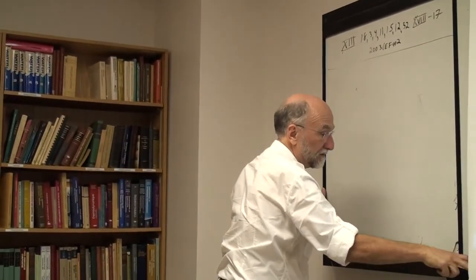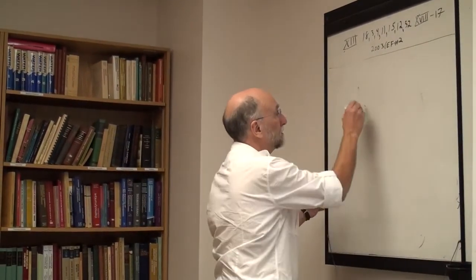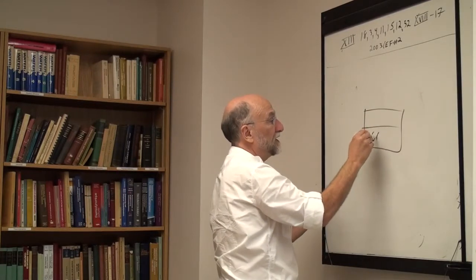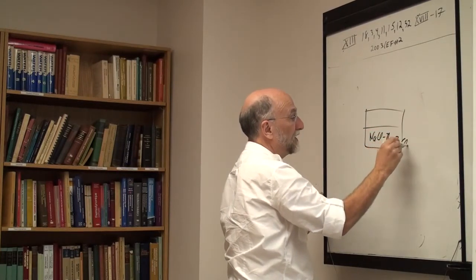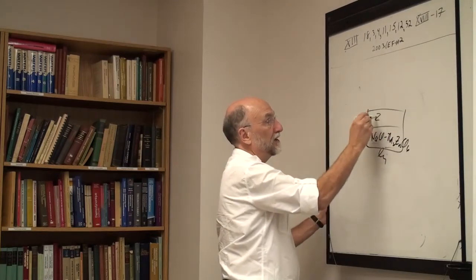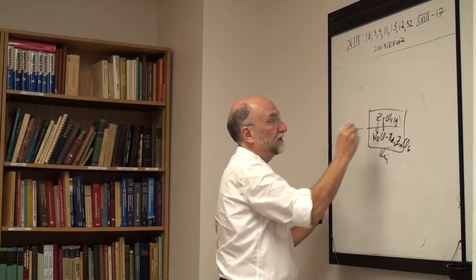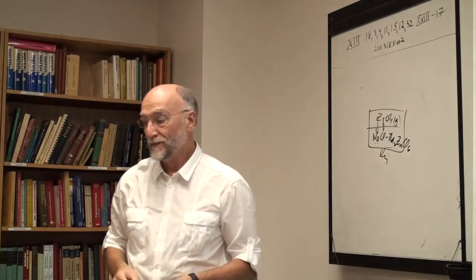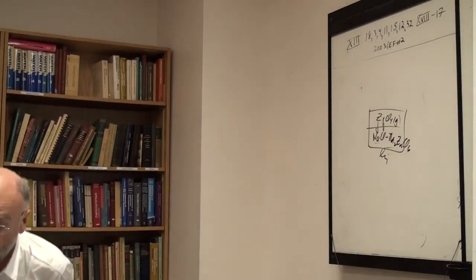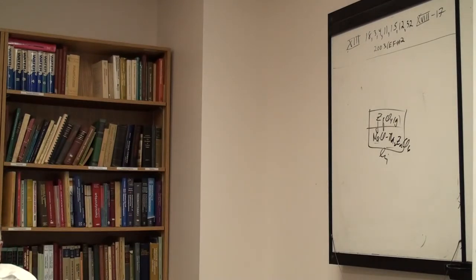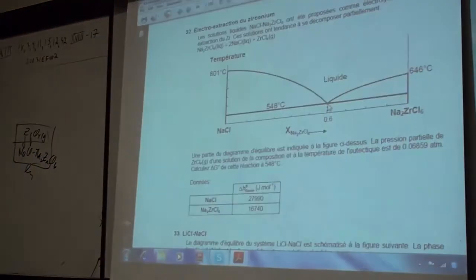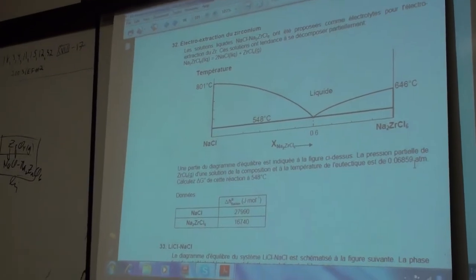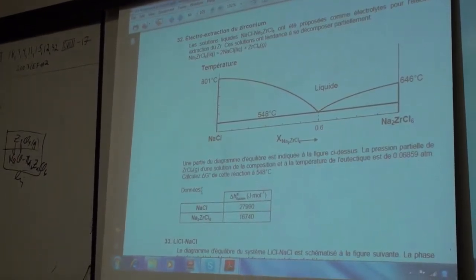So down here you would have your NaCl, Na2ZrCl6 liquid solution, and up here you'd have a ZrCl4 gas phase in equilibrium with it. Okay, the partial pressure has been measured at that point, at the eutectic point. The partial pressure of ZrCl4 has been measured as 0.06859 atmospheres. Calculate the Gibbs energy of this reaction at 548 degrees.